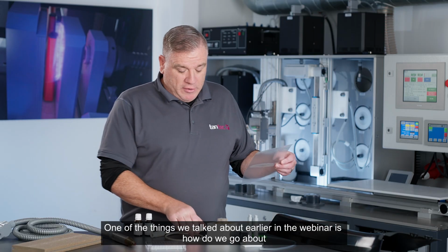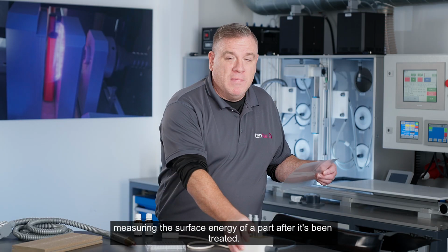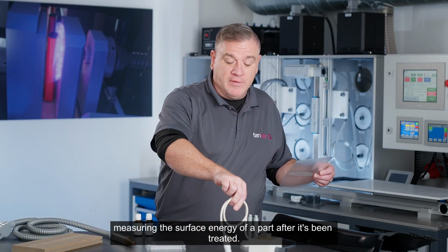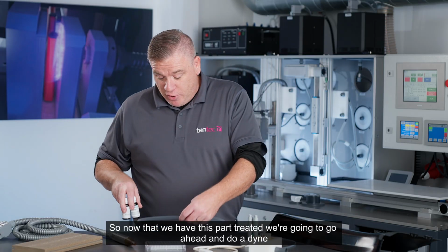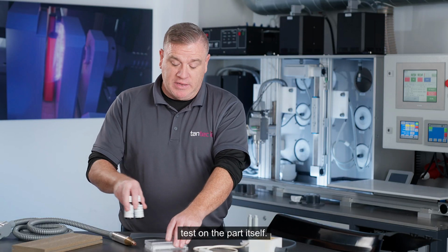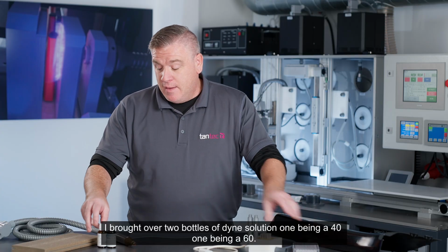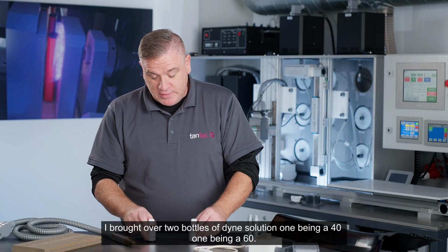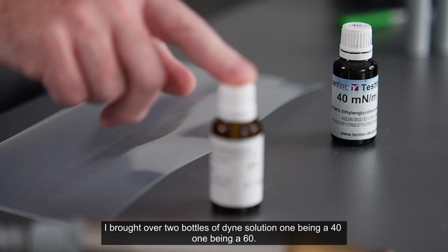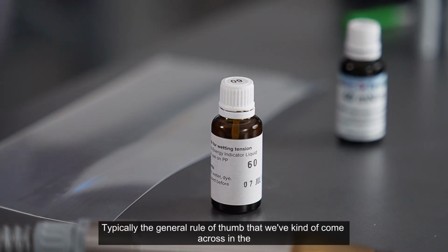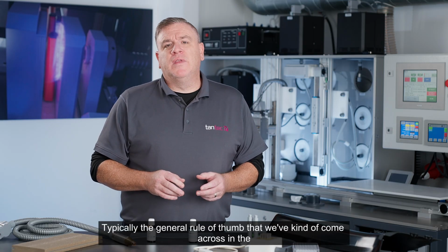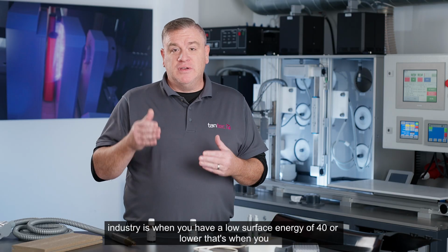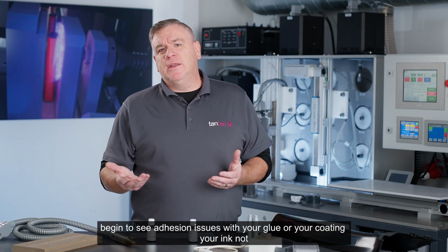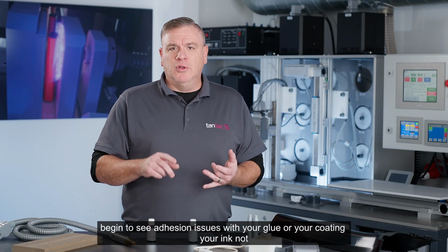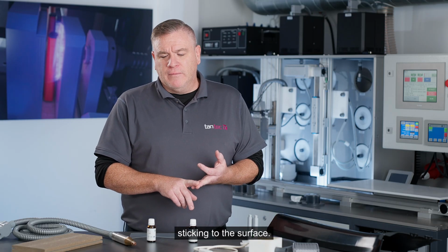One of the things we talked about earlier in the webinar is how do we go about measuring the surface energy of a part after it's been treated. So now that we have this part treated, we're going to go ahead and do a dyne test on the part itself. I brought over 2 bottles of dyne solution, one being a 40, one being a 60. Typically, the general rule of thumb that we've come across in the industry is when you have a low surface energy of 40 or lower, that's when you begin to see adhesion issues with your glue or your coating, your ink not sticking to the surface.